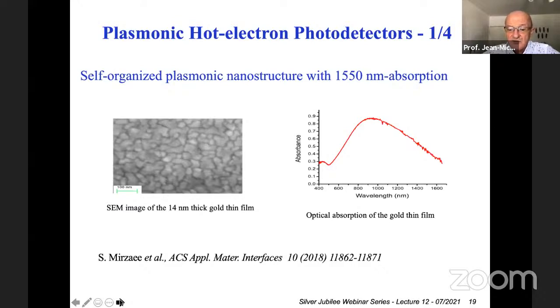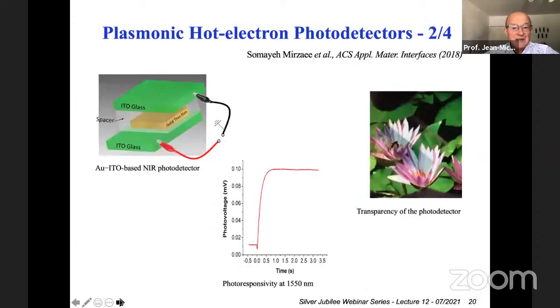With this random structure, which has a quasi-fractal structure, we can have an absorption that spans the infrared. Interestingly, it was absorbing down to 1.5, 1.6 microns. So we studied them with a laser at 1.5 microns. And we could see that we had the hot electron emission from these, as pictured by the photoresponsivity of a capacitor. So the device is just a layer of ITO deposited on glass, which we purchase, a gold film, which